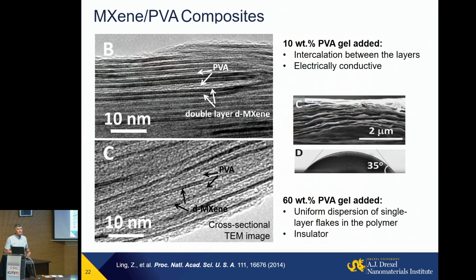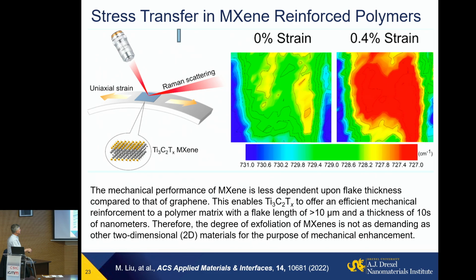And of course, we can assemble them with polymers and make composites. And what you see also, these flakes are very straight. This is in a PVA matrix. Because MXene, because of several layers, has bending rigidity orders of magnitude higher compared to graphene, which is flimsy because it's a very thin monolayer. These layers remain much thicker. And again, this is something that Eduardo has been doing, assembling polymers and 2D flakes long ago, but now we have 2D flakes with drastically different properties.